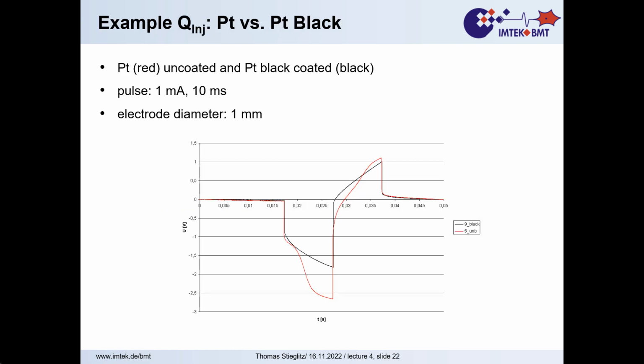This is here something where I got, always you do something, you put it on, and this is a good example of what you should not do, this slide. The black line is a reversible pulse. As you see here, this is voltage over time after a current pulse. So we applied the current pulse. And if you have that capacitive charging curve that you know from textbooks, then you're fine. If you overdo that, you get the red curve where you have funny changes in curve shape. And this is when you create whatever corrosion. Here you get an overpotential, and that could mean that you dissolve platinum particles from the surface that go somewhere. And if you reverse that, you get another shape. And if you do that more often, you lose your electrode.